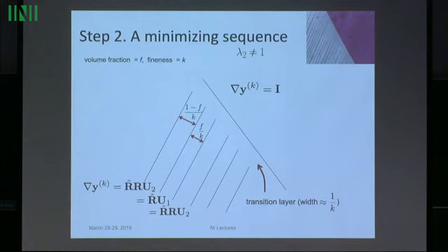But on the other hand, I simply can interpolate. Here's a deformation. It's now known. I've integrated this up. There's a deformation here. There's a deformation here. I interpolate them across this layer. And so there's a transition layer in here which involves gradients which are not on any of the energy wells. You'll be forced to use all kinds of other gradients.